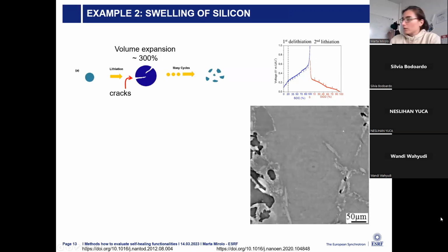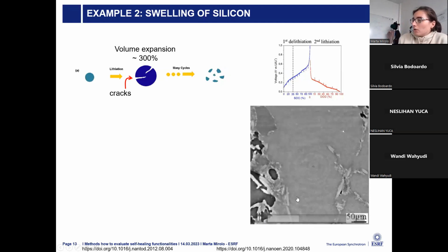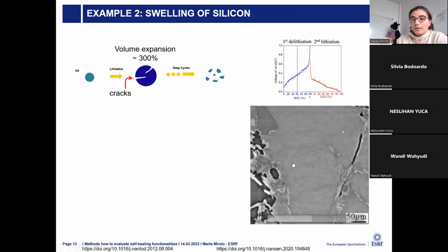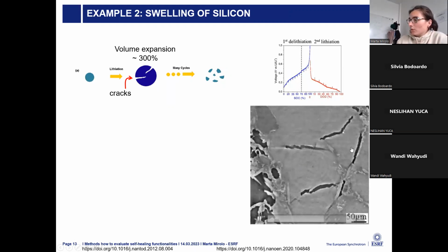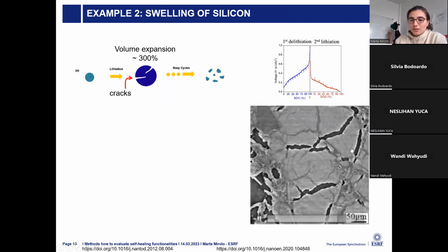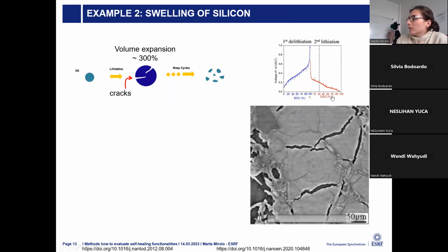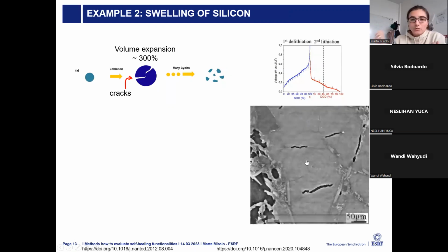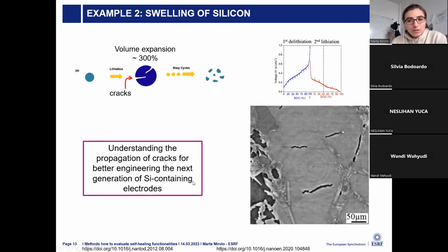And in fact, this is what, let me stop the video because this is really nice. So what we see here is a silicon electrode during delithiation. So we are removing lithium. So we see the formation of the cracks because the particle is getting smaller. And then during lithiation, the cracks are closing because we are reinserting lithium on silicon. And if we study that with different binders, then we can understand, for example, where the cracks are forming, if they are forming, and this leads to a better engineering for the next generation of silicon-containing electrodes.